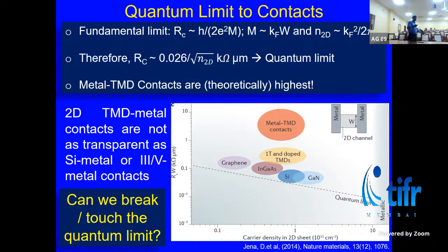So based on that, you know the quantum limit formula for the interface resistance, and then you can calculate it, depending on how much charge is present across the two sides, assuming you consider all states in the conduction band are filled, so you have all those charges present. Now what you notice is that graphene and the TMD are two orders of magnitude, 50 to 100 times, higher than what silicon can offer in terms of contact resistance. This is alarming, because if we want to harness the property and the contact becomes a limiting factor, the actual performance eventually is not going to be better than silicon.